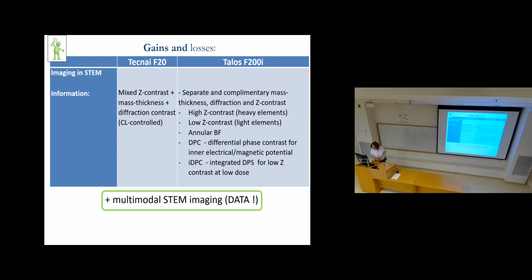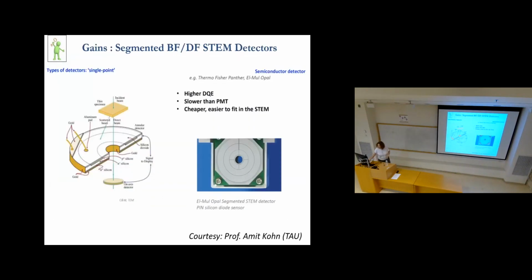With our new detection system, we have all these contrasts, but we can separate these contrasts one by one by simultaneously acquiring electrons scattered by different angles on the detectors having different acceptance angles. So this is the scheme of the STEM detector with a radial separation. So this is the annular dark field detector, and we have a few radial segments on this detector.